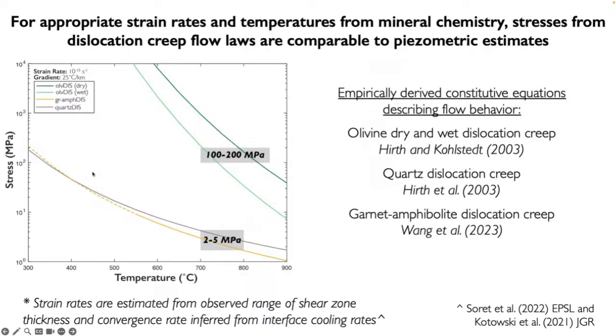And the last thing that I want to talk about is the significance of the inferred rheology from the metamorphic sole. So we can start to put quantitative constraints on rock strength and viscosity by using published empirically derived constitutive equations describing flow behavior, or flow laws. These are laws that are quantified in the laboratory by squishing rocks, and we can actually use these laws to make estimates about rock strength. So we can estimate appropriate strain rates for early stages of deformation based on the observed thickness of the shear zone and the inferred very slow convergence rates.